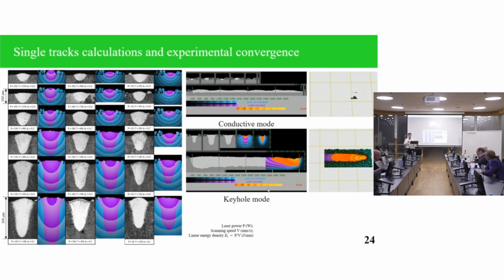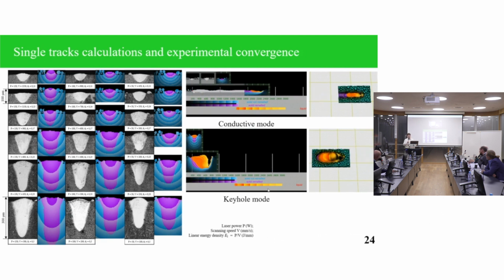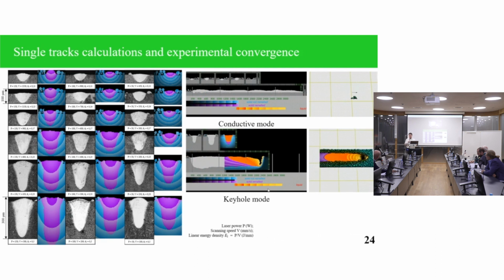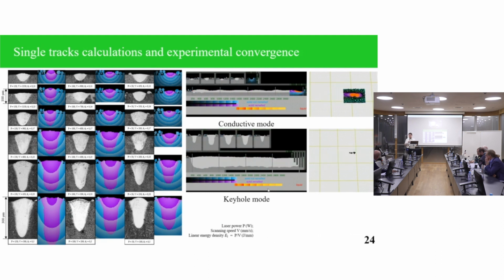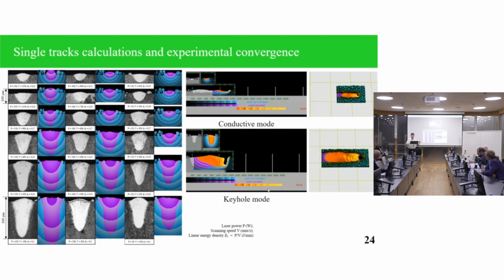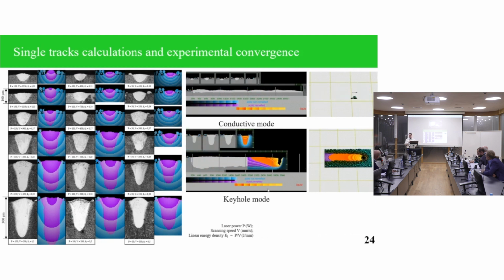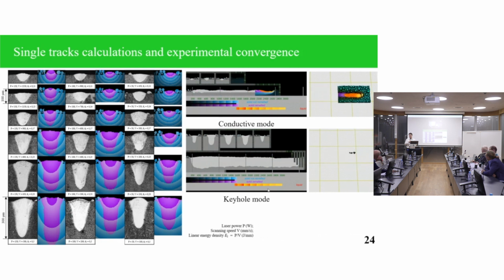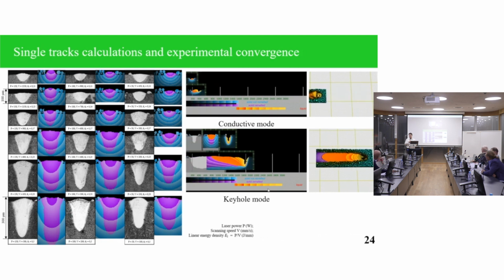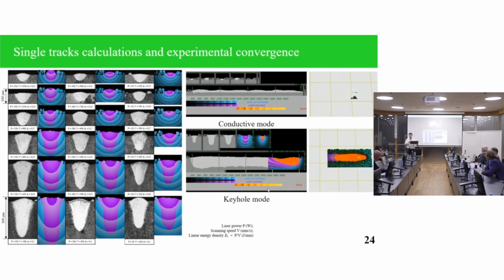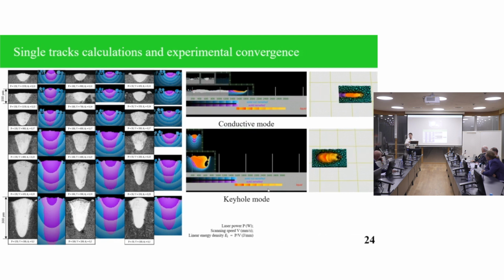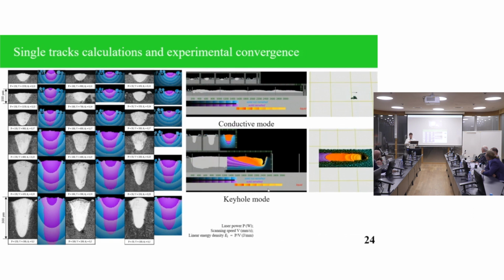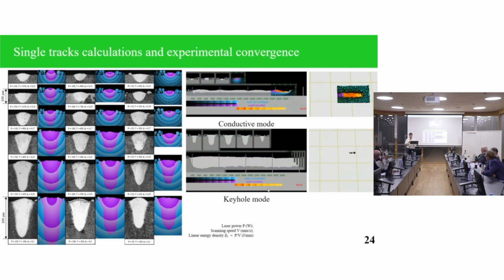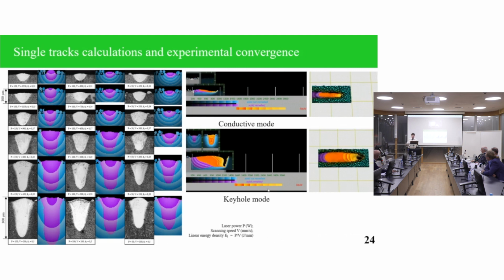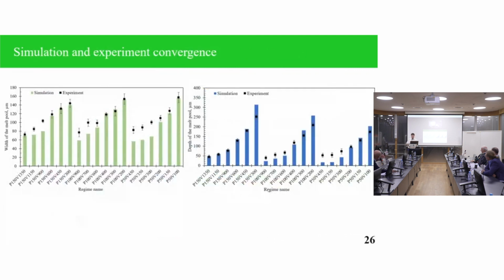In terms of comparison of the experimental and numerical results, actually on this slide the convergence is good. Because you say it's good. I don't particularly like it. Maybe it should be quantified somehow so that we don't remain at the level of emotional reaction, right? I mean, you can introduce some sort of measure of depth, width, which you did elsewhere in your thesis, and then you can compare how well. Yeah, on the left is not so good, on the right is pretty good, not always. Yeah, we agree, no?